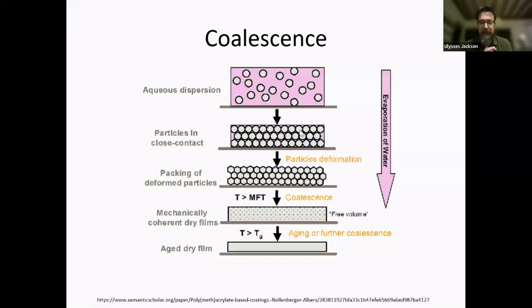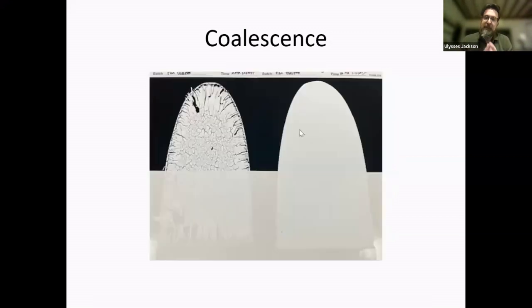It actually takes multiple years for a standard paint film to fully cure. And then finally, after it's had some aging, it shrinks completely down and you have that final cured film. So if you're using a binder that's too hard for the conditions, you'll get this cracking effect, which would be a really bad day at the office. And you can add something called a coalescing agent, a slow evaporating material, and suppress that Tg temporarily and get a nice film to form. And then that coalescent will leave and you'll get your final properties a little later.